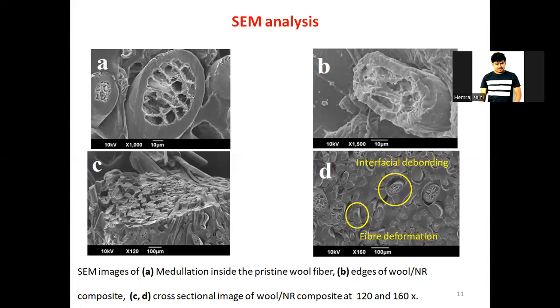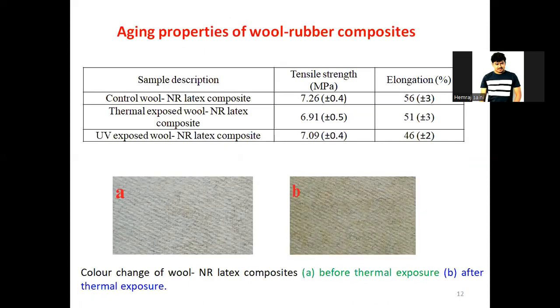Due to the tensile strain, the stress that we applied, interfacial debonding is observed. So that is the breakage reason during the applied stress. So these are the observations we got from SEM. And we also analyzed the aging properties, and you can see the tensile strength, aging properties in terms of thermal aging and UV aging. What we found is that after thermal and UV aging, there are no significant differences in the tensile strength and elongation, which indicates that the developed composite has good thermal and UV resistance.